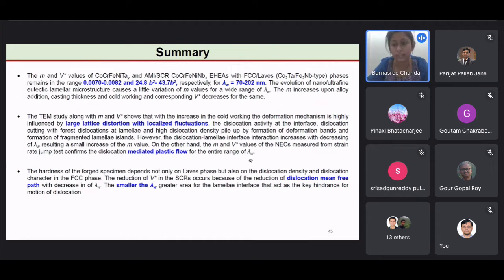The dislocation activity at the interface, the dislocation cutting with forest dislocations at the lamellae, and high dislocation density pileup by formation of deformation band can be seen. The strain rate sensitivity and activation volume measured from the strain rate jump test confirm the dislocation mediated plastic flow for the entire range of the average eutectic lamellae. Also, the reduction in the activation volume in suction casted rod occurs because of the reduction of the dislocation mean free path with the decrease of the average eutectic lamellae. The smaller the average eutectic lamellae, the greater the area of the lamellar interface that acts as a key hindrance for the motion of the dislocation.